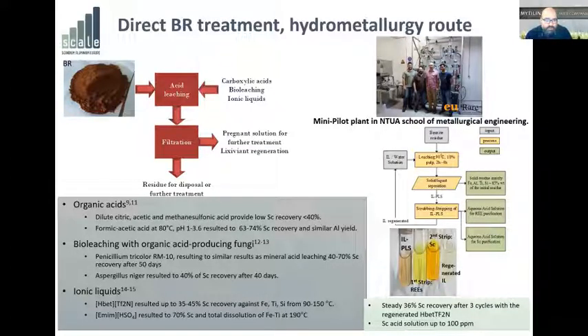And finally, there is some work with ionic liquids, which I'm very familiar with, where you can get up to 30 or 40% scandium recovery very selectively against iron, titanium, and silicon, or you can get up to 70% of scandium, but also with complete dissolution of iron and titanium. So on the right, you can see a pilot plant we did at the National Technical University of Athens at the metallurgical school, where bauxite residue was leached with this task-specific ionic liquid HBET TF2N,